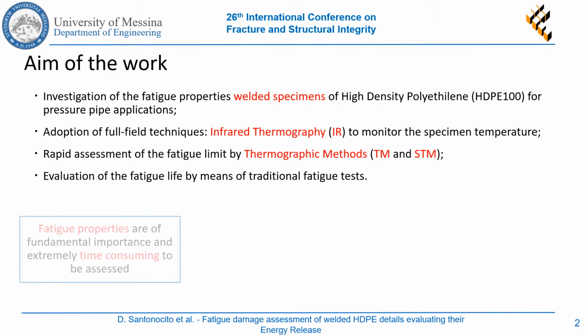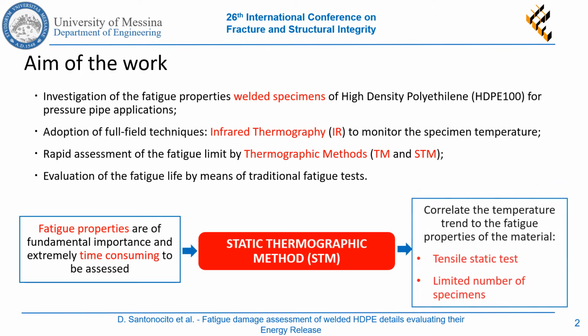In particular, the static thermographic method is proposed as a rapid test procedure able to correlate the temperature trend to the fatigue properties of the material during static tensile tests, adopting a very limited number of specimens.